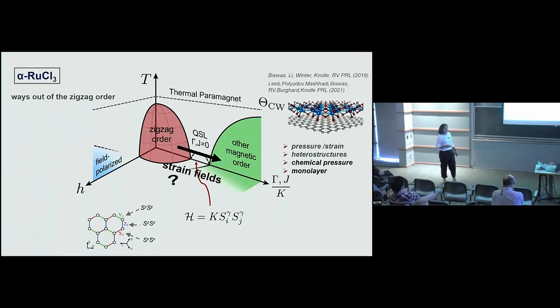I was showing that the magnetoelastic coupling is very strong in this system. So why don't we manipulate the magnetoelastic coupling in these materials and try to manipulate the exchange constants by manipulating the systems with strain fields? There are various ways of doing this manipulation. Of course, the simplest one is just to pressure the system, but pressuring the system is not a good idea, because when you pressure these systems, alpha ruthenium trichloride undergoes a phase transition into a dimerized phase, and that's it. You just get dimers.